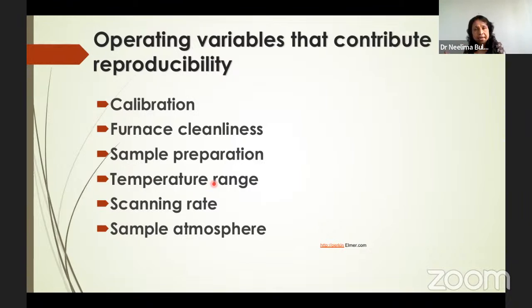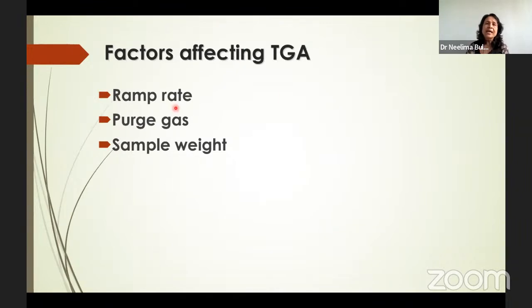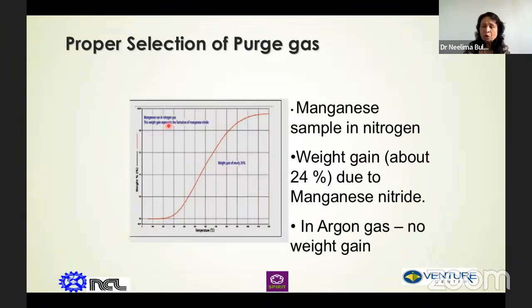Suppose your material is degrading at 800 degrees centigrade, and you record your sample up to only 400 or 500 degrees centigrade, you will end up with no information. Scanning rate is also important, because I will show you some graphs of how the data quality differs if you vary the scanning rate. Then sample atmosphere, which we have already talked about. The other factor is ramp rate, because if you change the heating rate, the onset of your degradation changes; it increases with the heating rate. Purge gas, we have already talked about. And sample weight, that I also told you: if you take a sample weight higher than the capacity of your balance, you are definitely going to land up with wrong results.